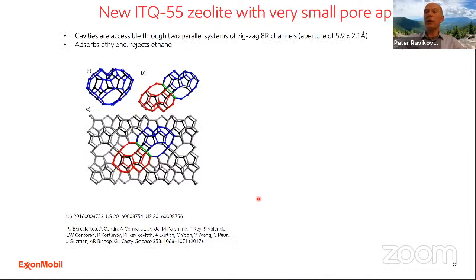Perhaps one of the most extreme examples of this coupling is the ITQ-55 zeolite. This is the zeolite we've been working on in collaboration with the group of Avelino Corma from Valencia. This zeolite has heart-shaped cages, and at the bottom of this cage you have two elongated 8-member ring windows. The nominal size of these windows, the minimal dimension, is 2.1 angstrom. This is way smaller than the size of typical molecules.